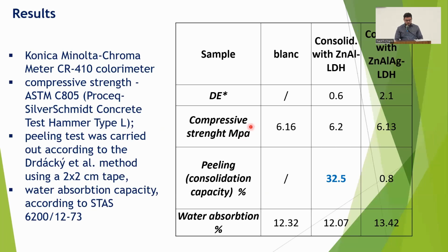In order to study their effectiveness as consolidants, after we dispersed the layered double hydroxide in the solvents, we brushed the test bricks 3 times on each side with the dispersion, and we let them some time to take effect. What's important is that the consolidants must not change the aesthetic parameters. We studied the difference in the chromatic parameters, and we observed that for both materials tested, the change in aesthetic parameters is not visible. So delta E, which is a parameter that shows the change in color, is less than 5, which is the observable limit by the naked eye.